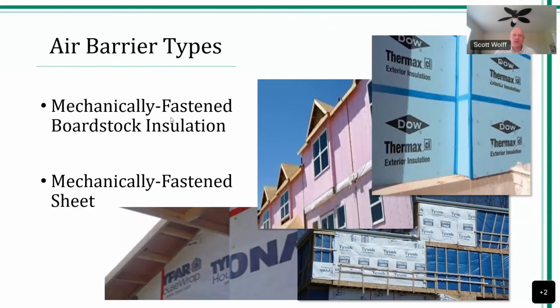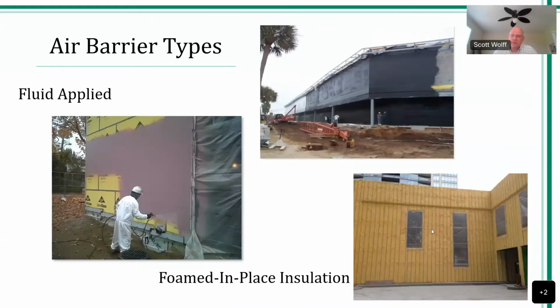And then of course there are these mechanically fastened board stock insulations, which again are recognized by the IECC as qualified as being an air barrier. So they resist air based on that E2178 standard. Same with the mechanically fastened. Now, the exceptions I would take to rigid board stock insulation, and for that matter, using spray foam as a standalone without any other elastomeric membrane behind it, is that they have virtually negligible elongation or tensile properties.